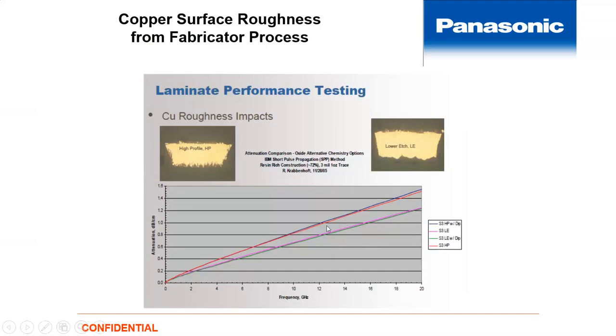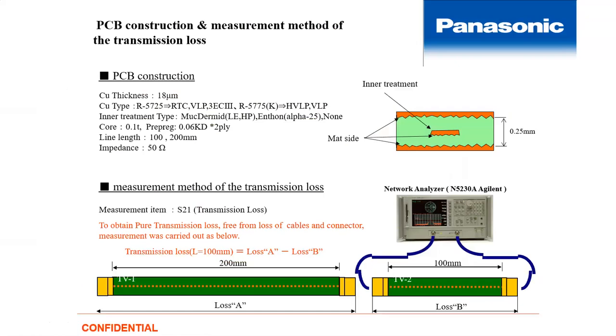loss. This chart is actually flipped upside down now, but the higher loss values are on the top side of the screen, and the lower loss values are here with the lower etch or the optimized oxide. So there's a whole way to go through and measure all this. This was just outlined. If anybody is interested in that, I'm not going to take the time to break that down, but there is a whole test method procedure for measuring that. It's the S21 transmission loss that they're pulling off of the network analyzer. So we can talk about that if anybody has any other questions with it.